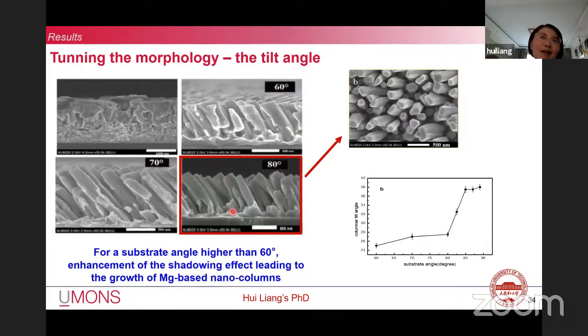Tuning the morphology and the tilt angle, we fix the substrate pressure at 0.26. And in the figure, the substrate angle increased from 0 to 89. We could find the deposit angle strongly depends on the substrate angle. And this could also be observed in the cross-section images of Mg. This can be explained by the influence of the atomic shadowing effects during deposition in GLAD, in particular at substrate angles greater than 60, where the shadowing mechanism is strongly enhanced.